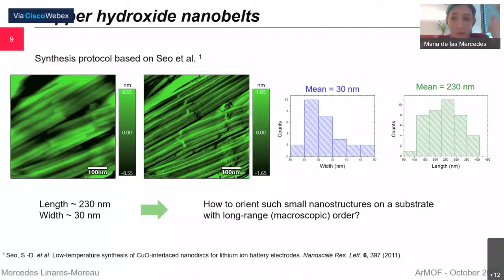If you saw, we never have one; the highest that we have obtained, maybe this might be improved a little bit, I think the highest was 0.85 or something. But I have also seen works where they model nematic systems, and there is a fundamental limitation when considering the aspect ratio of the nanobelts. So for this aspect ratio, there is not a lot of improvement that can be obtained just because of the dispersity of the nanobelts in sizes.